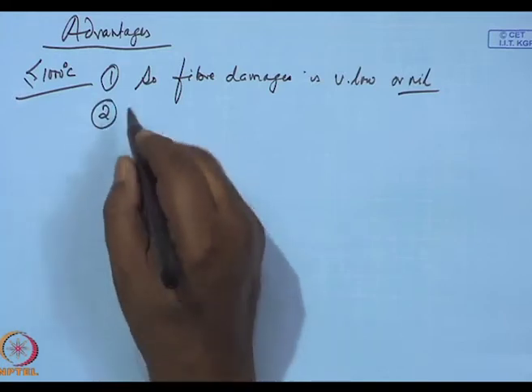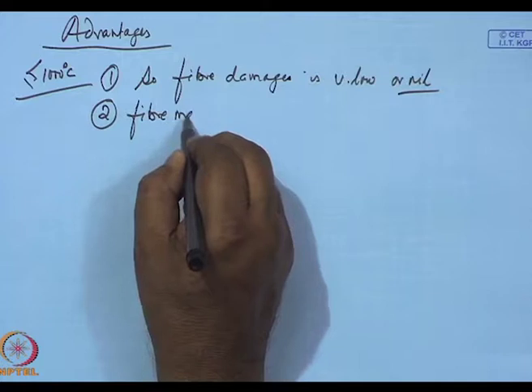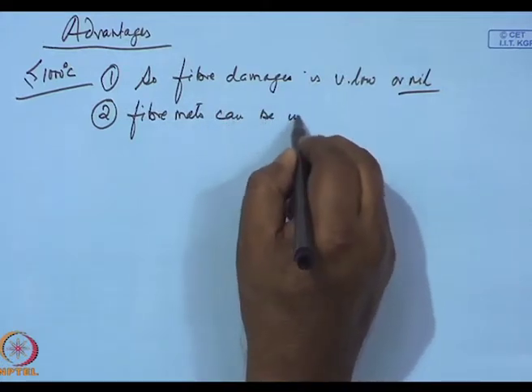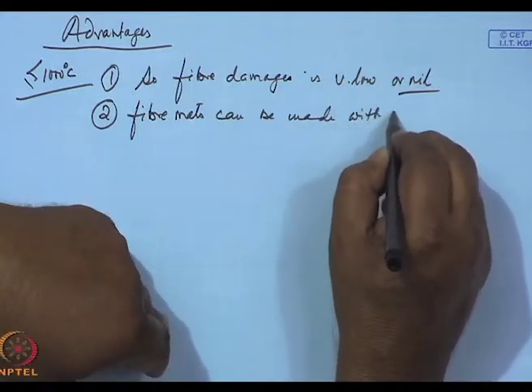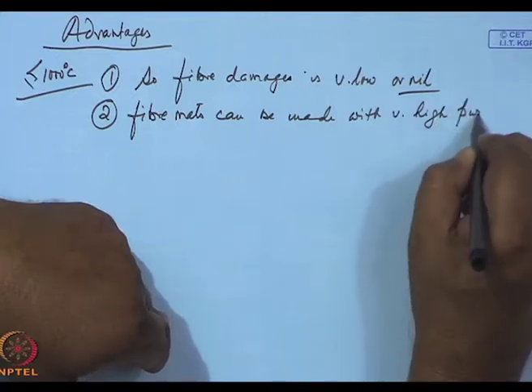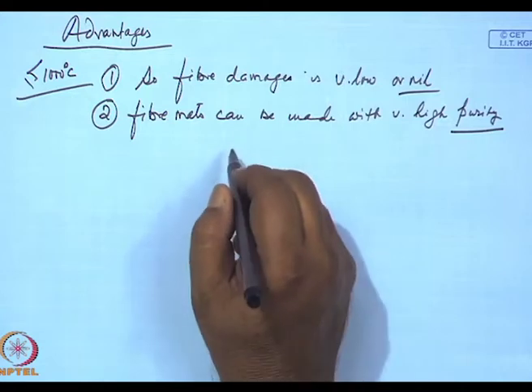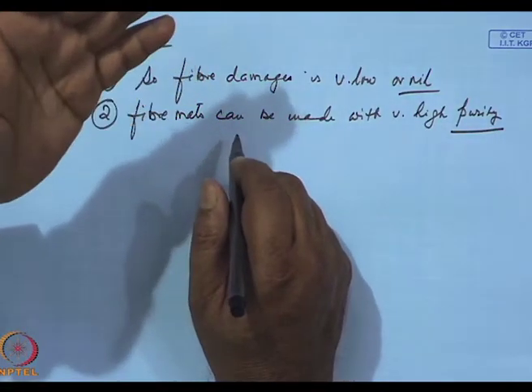Second, the fiber mats can be made with very high purity. For example, when I talked of alumina fibers in silicon carbide, what I had in mind was alumina fibers made from the alkoxide based sol gel process, in which case the alumina fiber mat is 99.99% pure. The advantage is I do not have any glass making phases. The material does not melt at low temperatures.